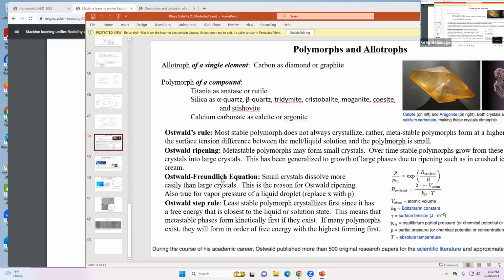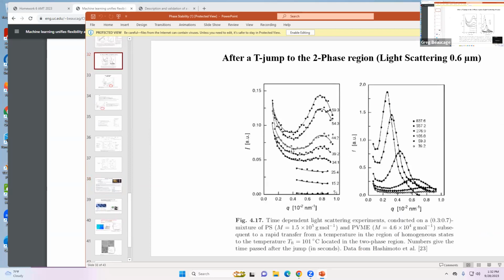That's been taken to mean things grow in size like this, but this is spinodal from polymers. In the early stage, you have a fixed size, that's the Q max, intensity versus Q. As time goes on, so 1 over Q is size, they get larger and the peak shifts to the left. That's termed Ostwald ripening in spinodal. It's like a late stage spinodal. And in the end, the peak just disappears and they just become dots as if they were nucleation and growth. So in the end, you can't distinguish between the things.